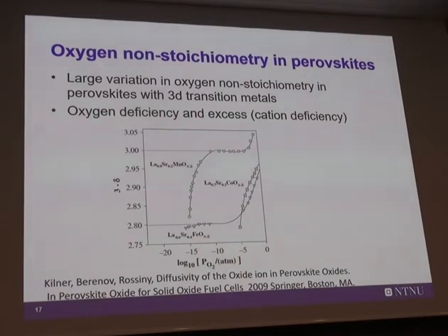And there are not so many systems which show this behavior, where you actually have more oxygen relative to this ideal stoichiometry. And it's in a way kind of stupid to say that it's 3.5 or something, because it doesn't make sense. So normally you have to renormalize the cation stoichiometry to less than 1. But that's hard to write and hard to calculate, so people normally do that with 3 plus delta instead. But there are not many examples of that in literature. This is one of the most classical. The other one is the cobaltite.